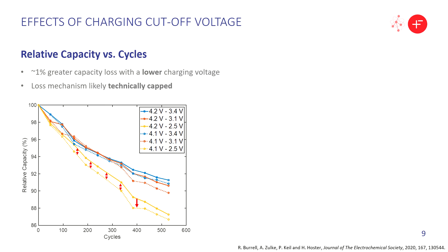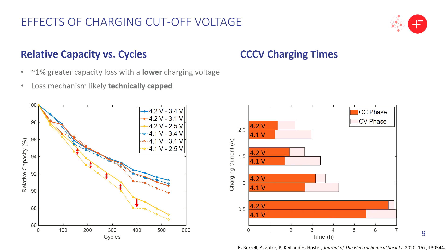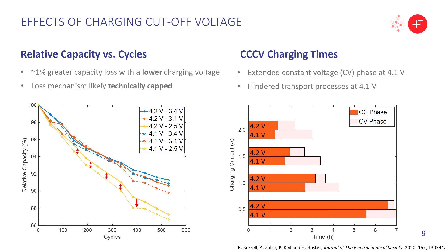To dive a little bit deeper into the differences when charging to 4.1 volts versus 4.2 volts, we conducted a timing study to look at the charging times to these different voltages. We see here, at four different current rates, the time taken to charge to either voltage with a breakdown of the constant current and constant voltage phases. We can instantly see that charging to 4.1 volts actually takes longer than charging to 4.2 volts. Observing the breakdown between the two phases, we see a significantly extended constant voltage phase at 4.1 volts, leading us to believe that we have hindered transport processes occurring at 4.1 volts.